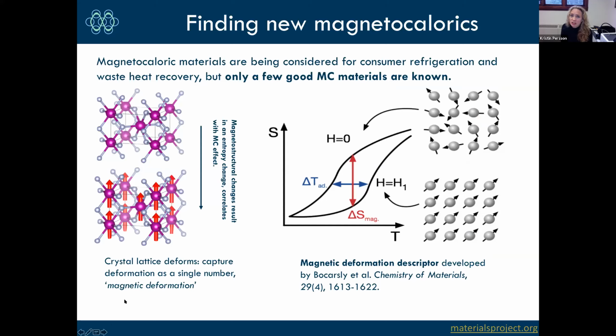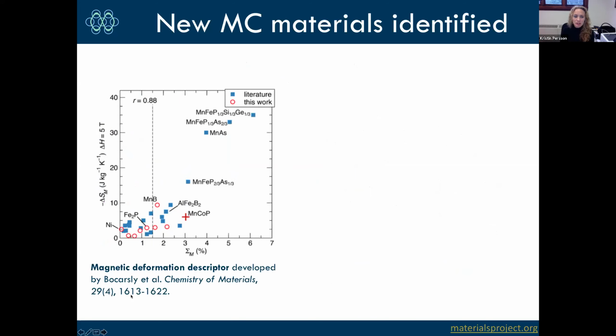So Magneto-Caloric materials are materials that are being considered for things like consumer refrigeration, basically replacing the compressor technology, and waste heat recovery, but there are only a few of these materials known and they're highly engineered. So it would be good to have new beginning materials that you can then optimize further. The whole idea is that you're switching a material from a paramagnetic to a ferromagnetic state with the help of a field. And if that magnetic transformation couples to a structural transformation, you tend to get a large change in entropy, which is associated with a change in heat. So you can basically absorb and desorb heat with the switching of your field and your material's magnetic and structural properties.